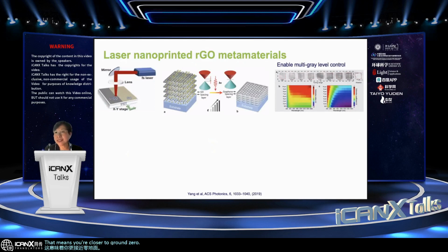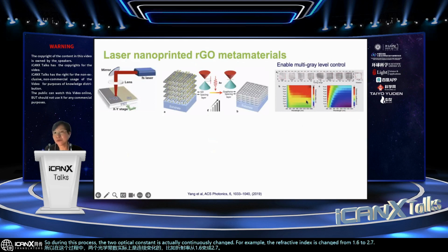So during this process, the two optical constants are continuously changed. For example, the refractive index is changed from 1.6 to 2.7. So this is a huge change. Remember, this is for a very thin layer of graphene oxide. And this change is about 2 orders of magnitude higher than normal bulk material. In the meantime, the extinction coefficient is also changing very dramatically.